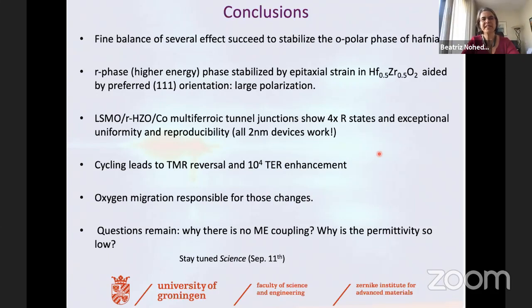I believe in the group of Thales, Agnès Barthélémy and Manuel Bibes and collaborators, they have shown, if I remember correctly, tunnel junctions with STO and cobalt showing a similar effect. And they reported at that time that it was not the LSMO, but the cobalt. So that's one reason. And the other reason is, I didn't show it here, but we actually saw on TEM that the cobalt is oxidized at the interface. So that can happen. Oxygen vacancies move, oxygen moves all through, and there is a lot of exchange at the electrodes.